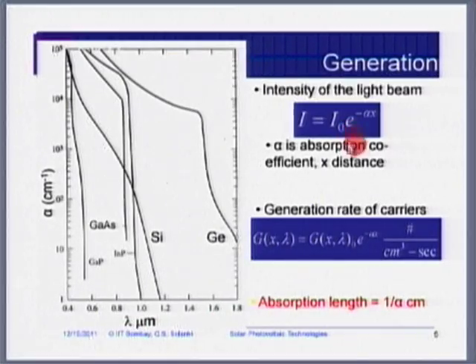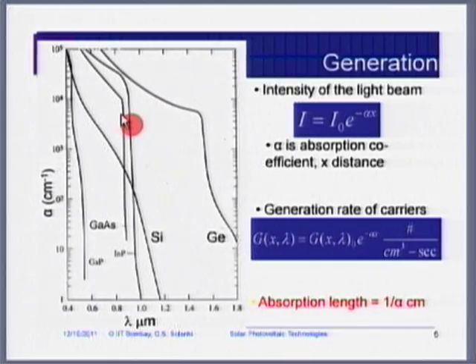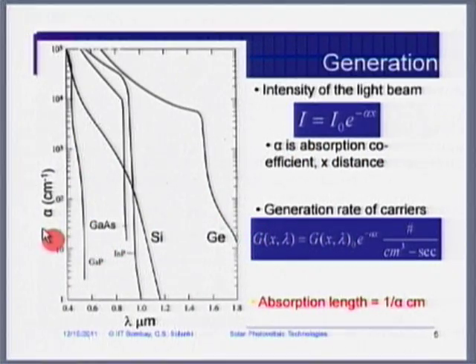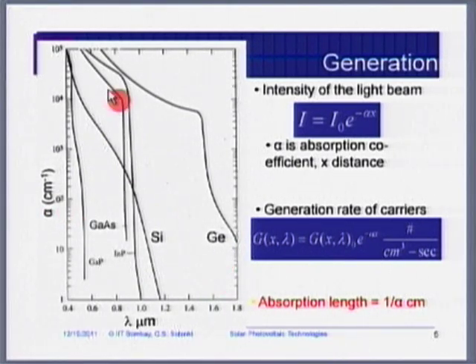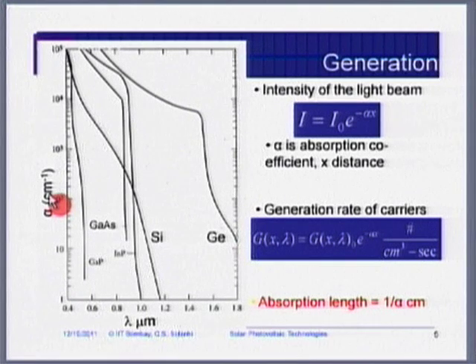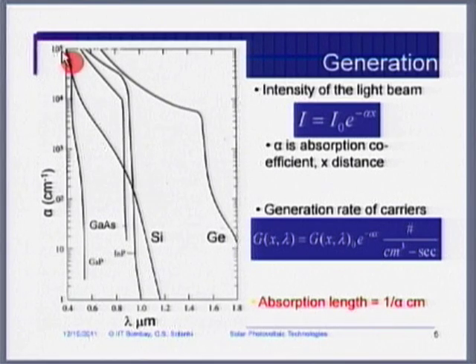Energy must be greater than or equal to the band gap energy. How do we know how much absorption takes place? The absorption probability depends on whether the material is a direct or indirect band gap semiconductor. How much absorption occurs is given by a factor called the absorption coefficient, denoted alpha, with units of inverse length — 1/cm. Looking at absorption coefficient values: 10⁵, 10⁴, 10³, 10², 10, and 1.